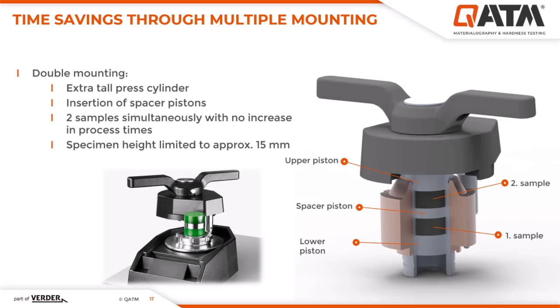Machines designed for double mounting are typically equipped with a tall press cylinder as standard. In this press cylinder, the first sample and the mounting material is placed at the bottom. A spacer piston is then inserted here, and a second sample with a corresponding resin for the second mount can be added. The height of each finished mounted sample is limited to around 15 millimeters, which is sufficient for most applications. A key advantage is that the spacer piston is very cheap, and this method allows you to quickly and easily double the sample throughput in your lab.